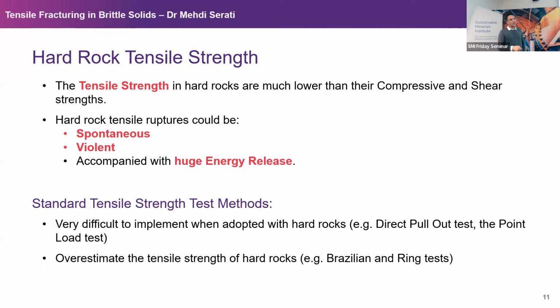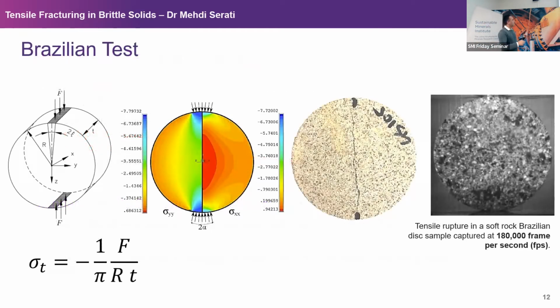And most of the time, when they are applied to hard and stiff rock, they tend to overestimate the tensile strength. And this is unfortunately a point that is largely ignored. Let me give you an example. The Brazilian test: you have a disc-shaped sample, you apply a concentrated line load at the two ends of the diameter, and if you have the geometry of the disc and the load at failure, you plug it into this beautiful yet elegant equation, and it gives you the induced tensile stress. But, as you can see in this high-speed photography, it is only valid if the tensile crack initiates at the center and propagates toward the contact area,